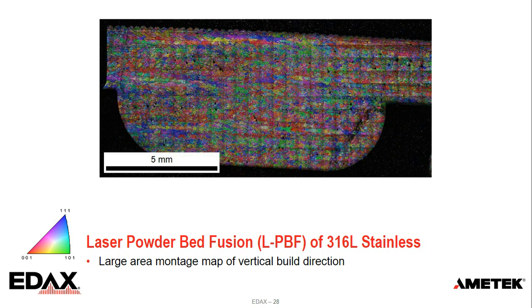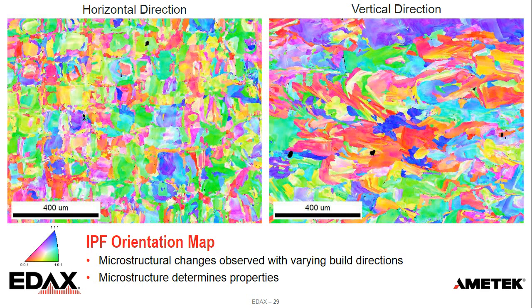Looking at these at a little bit higher magnification, you can see that the microstructure is very different between the horizontal and vertical directions. And this is essentially part of how the energy beam interacts with the particles, the solidification and heat transfer rates, and then how it goes from one layer to the other, the direction of the rasters, and there are a lot of things going on in there. And again, if you're able to adjust your build parameters to adjust your microstructure, and microstructure determines properties, being able to measure your microstructure is a key component in really moving forward with this.